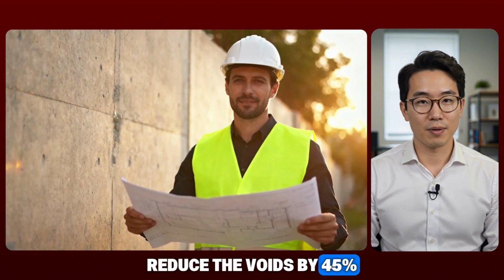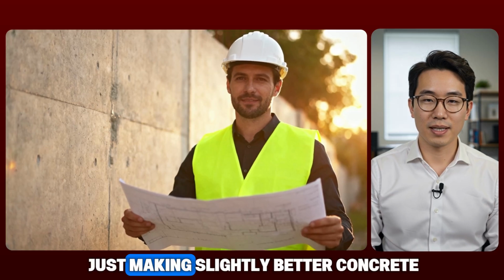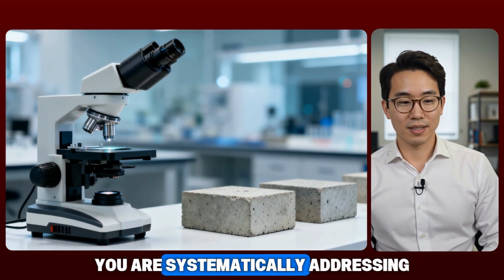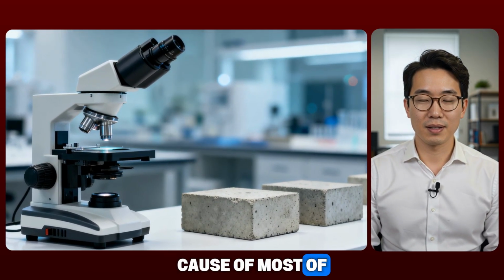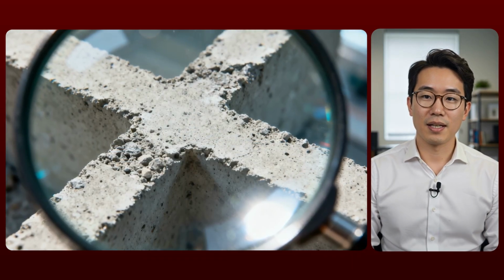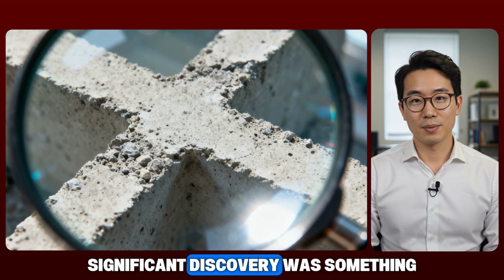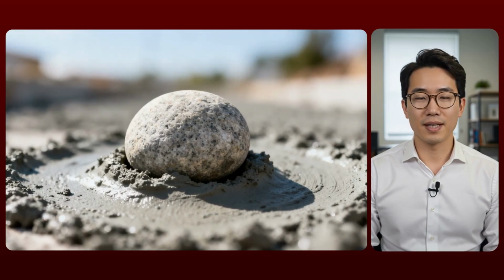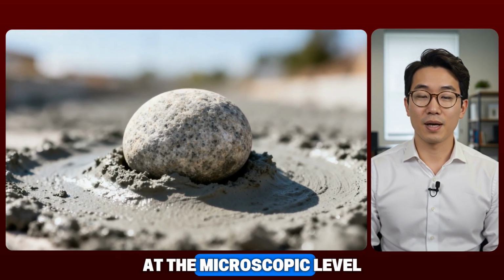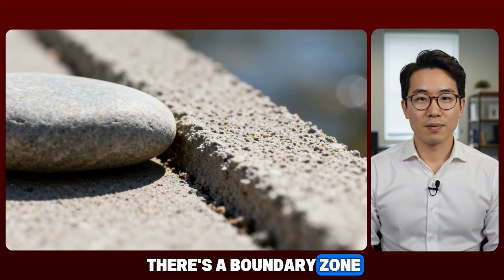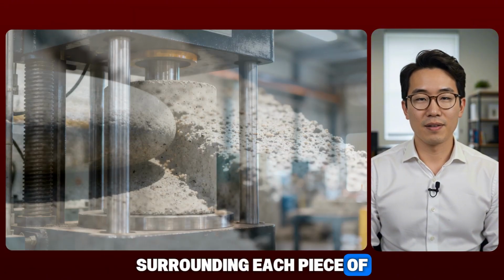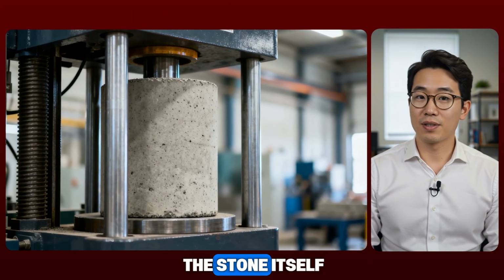Reduce the voids by 45%, and you are not just making slightly better concrete. You are systematically addressing the root cause of most of the ways concrete fails. But the most significant discovery was something even more specific. Inside every piece of concrete, at the microscopic level, there's a boundary zone where the cement paste surrounding each piece of aggregate stone comes into contact with the stone itself.